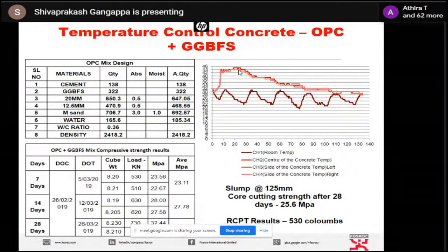That's all. So here, how can we do the controlling of temperature? The controlling of temperature can be done in different ways. One is to use a high volume replacement of GGBFS, or in addition to this, use chilled water and maintain the concrete temperature less than 32 degrees centigrade at the time of pouring. So these are the few parameters which we have to follow. And once the concreting is done, immediately we have to cover it with polyethylene sheet, so that the difference between your ambient temperature and the core concrete temperature will be less.